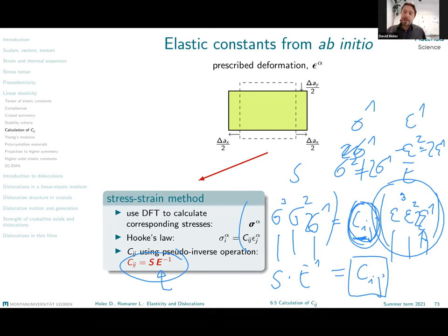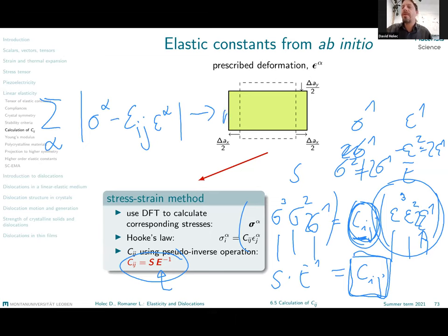So what I need to do in the pseudo-inverse is find a matrix which minimizes the residue. For each stress, I get the predicted stress based on the strain. Now I need to minimize all those differences for different alphas. This is the principle of the pseudo-inverse. So the matrix will be minimizing this difference. In other words, we are searching for a matrix which best describes the given data set, which should relate stress and strain.